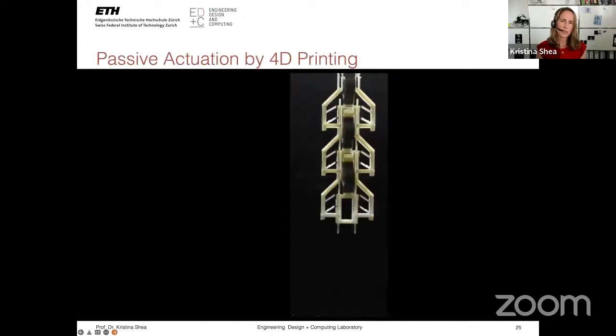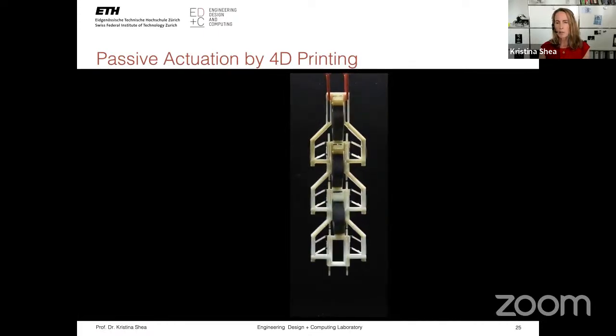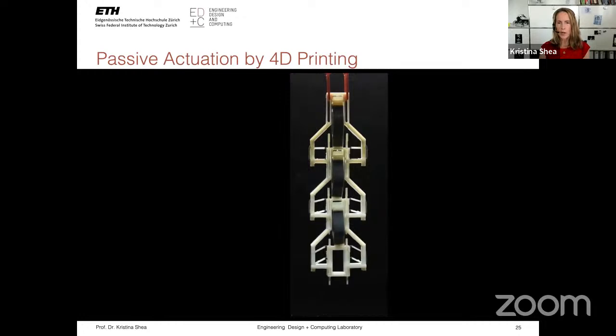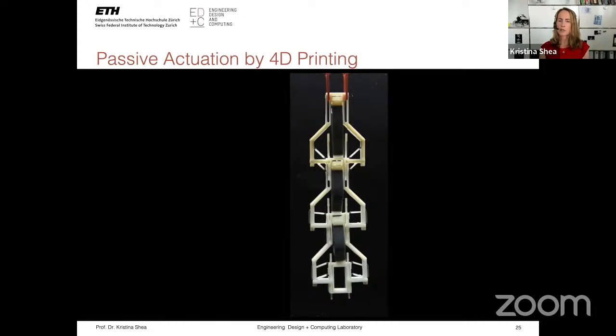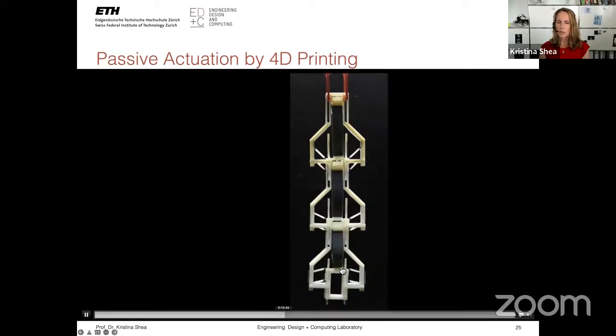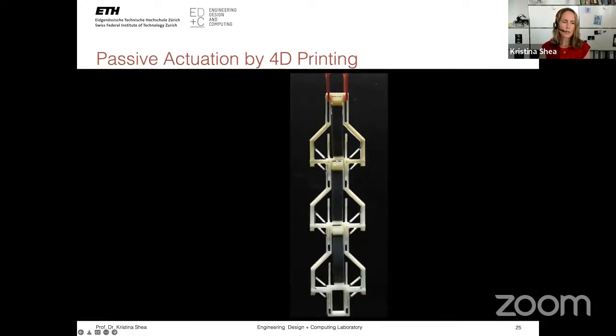So the next step was then to be able to actuate these automatically. And so it turns out that these Connex materials are shape memory polymers, which is highly advantageous for us. And so the next step was to add these shape memory polymer strips to be able to activate the structures automatically. So it's still the same bistable joint, but here it's activated by these black strips that you see here in the middle. And they can be designed such that the timing is such that the first opens, then the second, and then the third. And so that creates this passive actuation by temperature.